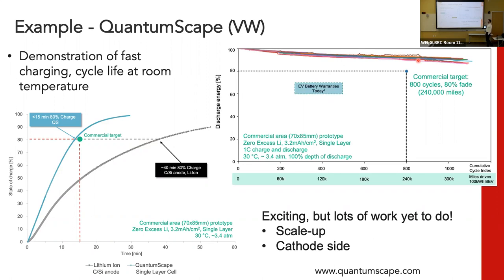So over here on the left side, we're going from 0% state of charge up to 80% state of charge in 15 minutes. This is compared to kind of state of the art Tesla battery, essentially, what that can do, 40 minutes. And then we can cycle it 800 times here. So this is, by some metrics, the most exciting solid state battery performance metrics that are out there. There are other big companies.